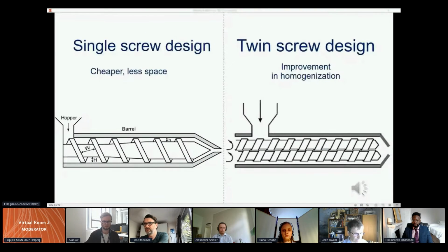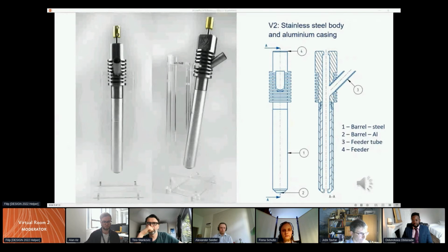The screw design has a significant impact on the dispersion of the additive throughout the matrix. On one hand, twin screw design assures better material mixing. On the other hand, we wanted to keep the design simple. The extruder was developed in several iterations. A modular design was used. Parts were created and assembled in different combinations. Heat and wear resistance of materials were considered too. At the end, the decision was taken to use the single screw extruder design due to space constraints and promising test results.